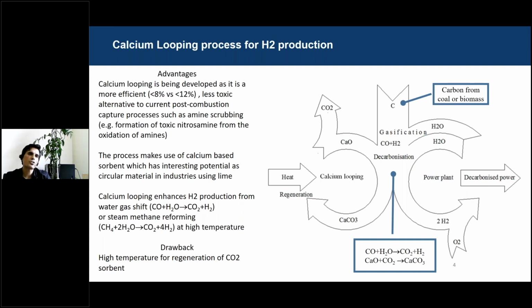So the water gas shift, which is the reaction of CO with the water steam in order to produce CO2 and hydrogen, can be coupled with the removal of CO2 with the calcium oxide. The net result of those two reactions is calcium carbonate and hydrogen, which can be used as a fuel or as a reducing agent in the steel industry. And the calcium carbonate can be sent to a calciner in order to close the loop and to start again the decarbonization of the syngas.